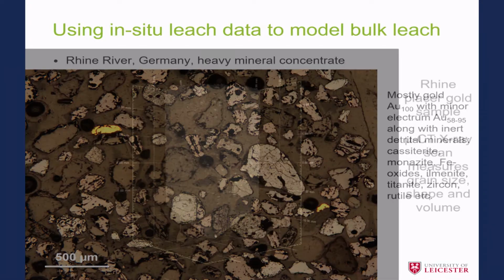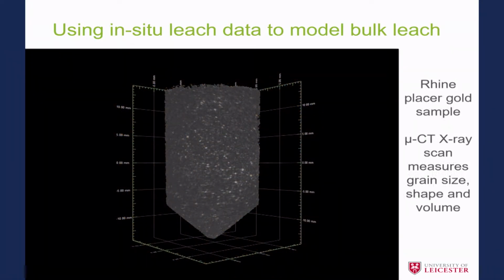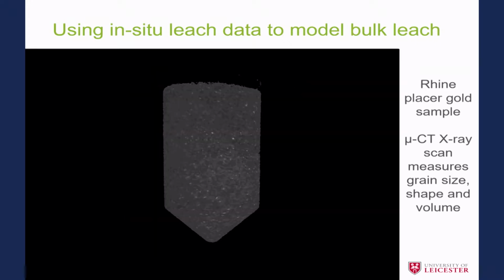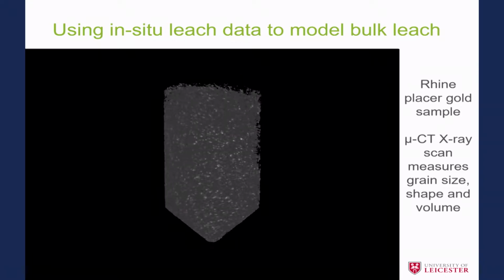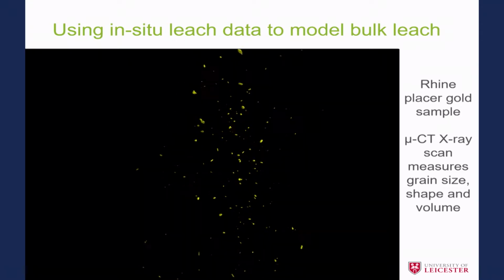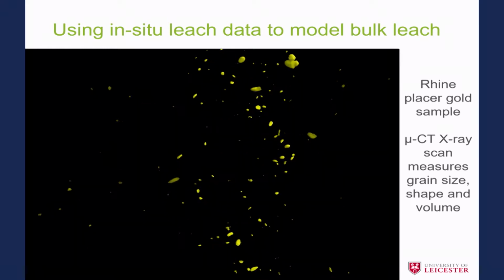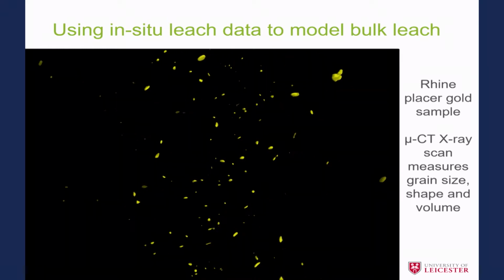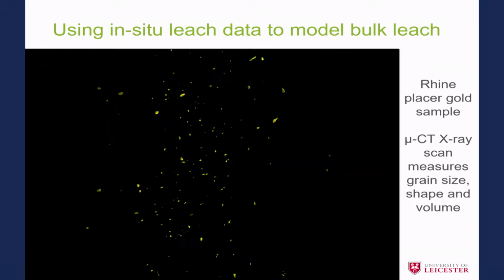So what we've done is take our sample and put it in a micro CT X-ray scanner and look at it in 3 dimensions. And this allows us to pick out all the gold grains and look at their size and shape. Okay, at the back. Okay, here we go. Okay, so we can pick out the gold grains, we can see exactly how big they are, and we can measure those very precisely.